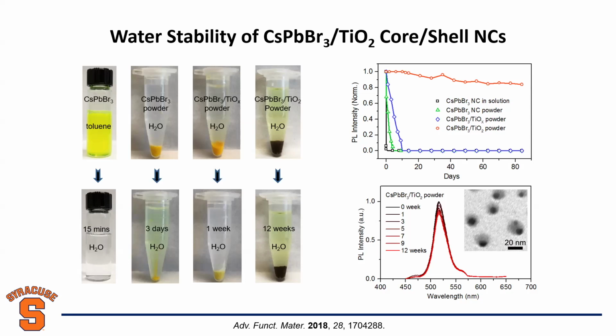Really, core-shell growth is not new, but if you want to grow core and shell epitaxially, you need two requirements. First, core and shell have the same crystal structure. Secondly, they need to have very similar lattice parameters, or very small lattice mismatch, so you can grow atom on top of atom, right? Very similar structure, similar spacing between atoms.